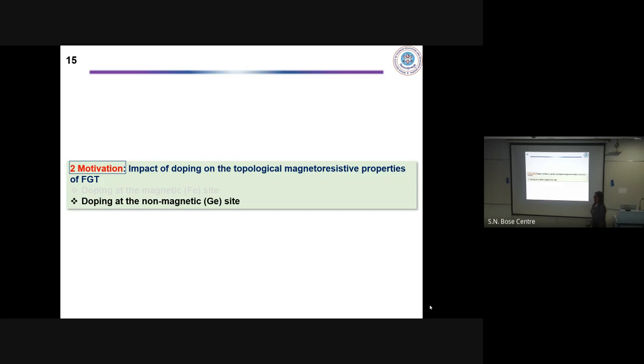So it reduces the magnetic moment. The transition temperature also decreases. Does it bring any frustration or change the exchange? Maybe this cobalt compound, if it forms, is completely diamagnetic, like nickel, Ni3Ge2, completely non-magnetic. It has been seen in the case of nickel doping also that it doesn't obey the Slater-Pauling curve. Basically nickel is kind of non-magnetic in these systems, like it happens to be in the nickel telluride cases also.